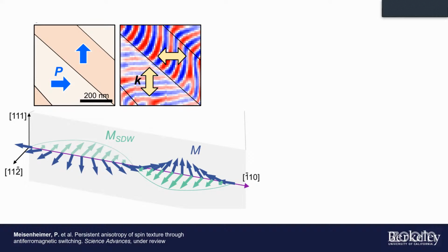The way we do this is with what's called a scanning NV magnetometer. And so we have a single crystalline diamond scanning probe tip, so we can do spatial mapping. And an NV center acts kind of like a trapped ion or an individual ion, which makes it very sensitive to Zeeman splitting from very small magnetic fields. If we look at that splitting as a function of space, because we're in a scanning probe technique, that allows us to map out these very, very small magnetic fields of 1 to 2 Oersted at the surface. And that's really what enables this technique.